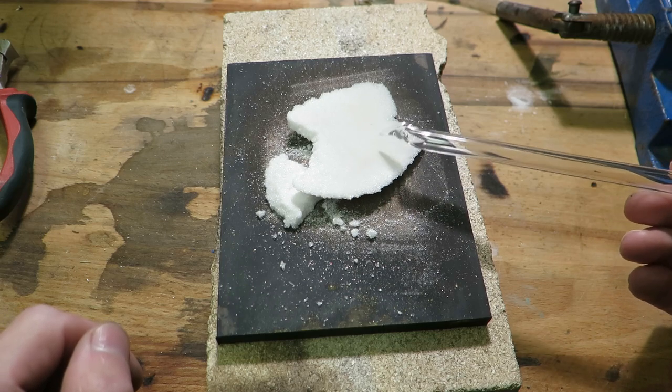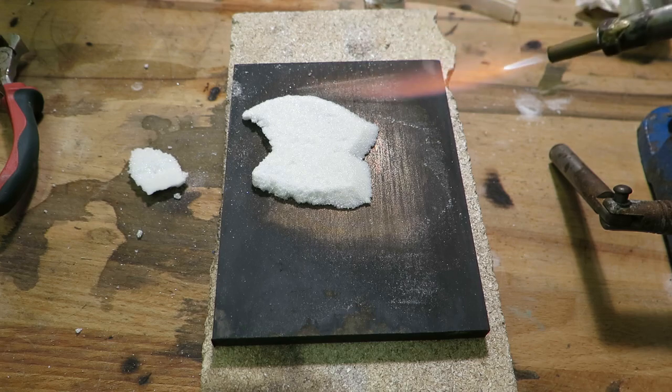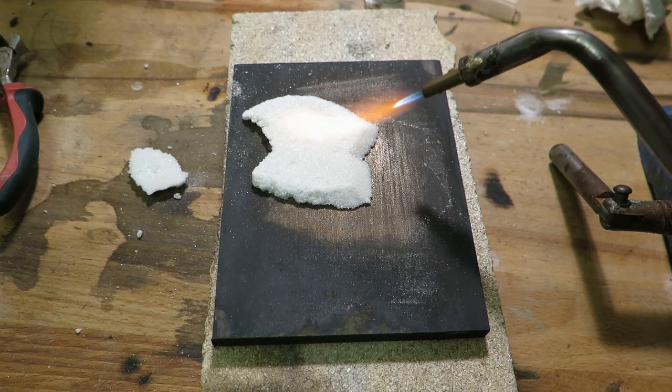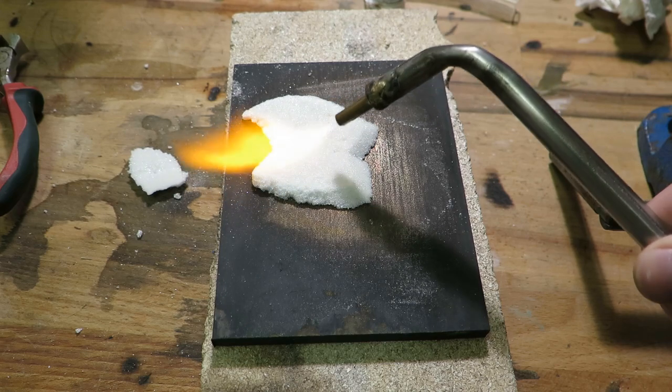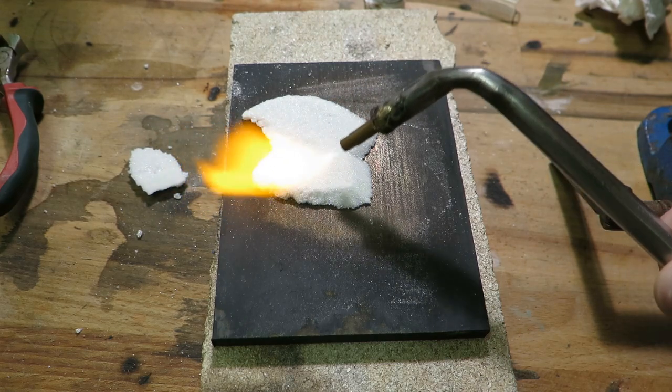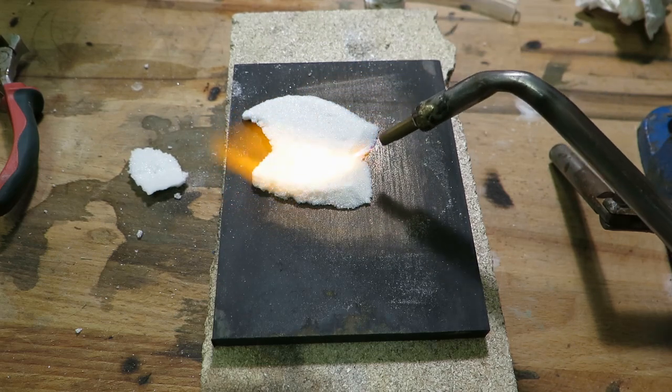The top side is quite loose, and the bottom side is very flat and almost mirror-like. The top side is obviously quite crumbly, and the bottom is pretty good actually. I used a torch to treat the top side a little bit, and it worked quite well.